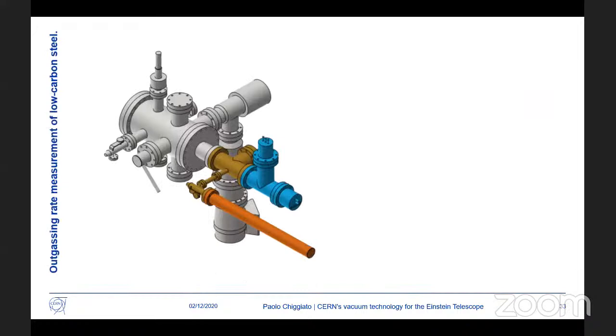Then after that, we measured the outgassing rate of samples and vacuum chambers. For that, we have 3 different ways to measure it, and I present here only the most sensitive. In this system, we have a measuring vacuum system with gauges and a quadrupole mass spectrometer. This brown chamber here is where we have the installed samples, or the chamber itself can be the sample. We process the vacuum system as usual with the bakeout. We apply the bakeout that we want to the chamber or the sample. Then when everything is at a good temperature, we close this valve here, just close to the brown sample, and we let the released gas accumulate into the chamber itself, the brown one.